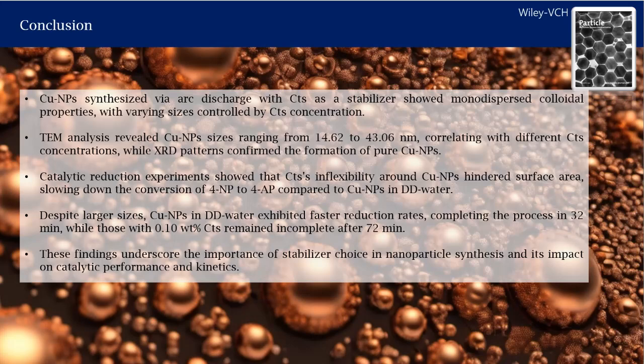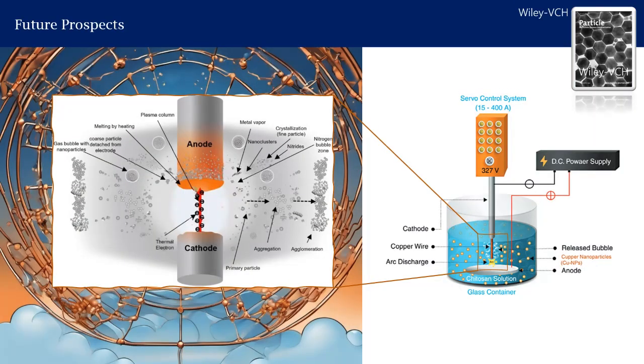TEM analysis shows nanocopper sizes ranging from 14.62 to 43.06 nanometers, correlating with different chitosan concentrations, while XRD patterns confirm pure nanocopper formation. Catalytic reduction experiments reveal that chitosan's inflexibility around nanocopper hinders surface area, slowing 4-nitrophenol to 4-aminophenol conversion compared to nanocopper in double distilled water.